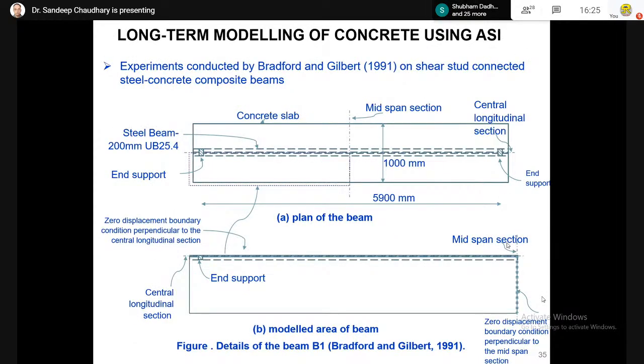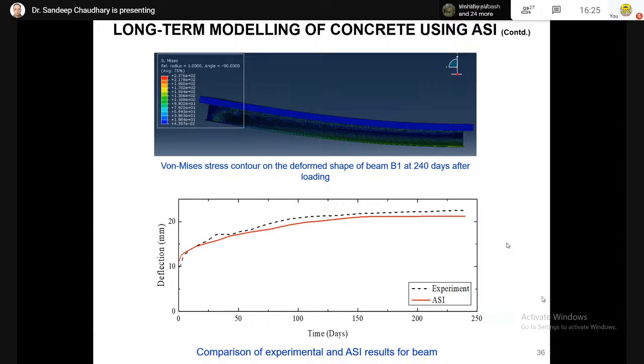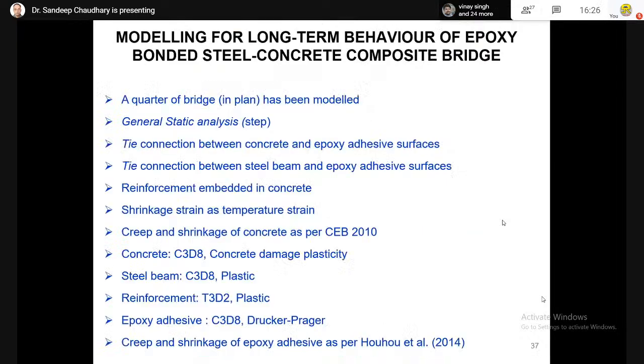And so there were certain scripts also which were written. The reason is that in Abaqus, there's an inherent disadvantage that you cannot use cracking and viscoelasticity, that is cracking and creep phenomena, together. So to take these two phenomena together, you have to use some scripts. So those scripts were written. And here you are seeing long-term results, even up to 250 days, more or less they're in agreement. So finally, that gave us confidence in the model for this epoxy bonded connection.